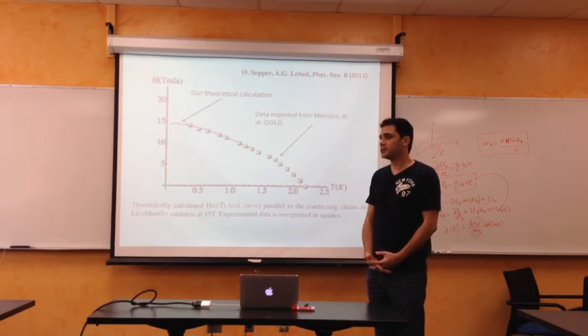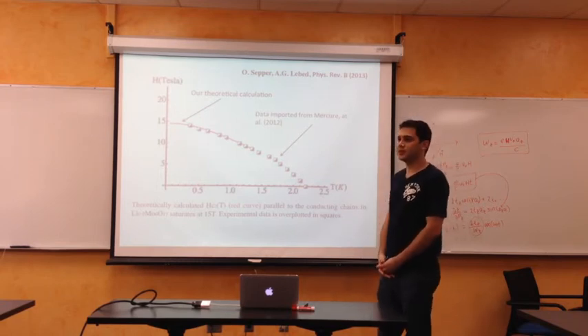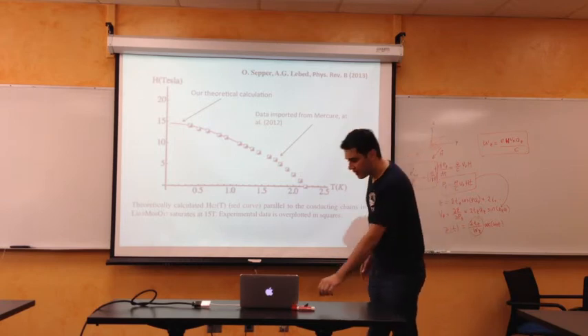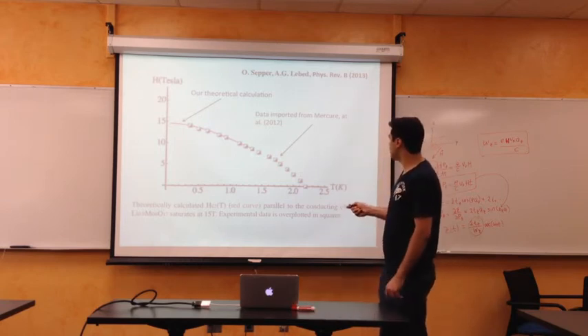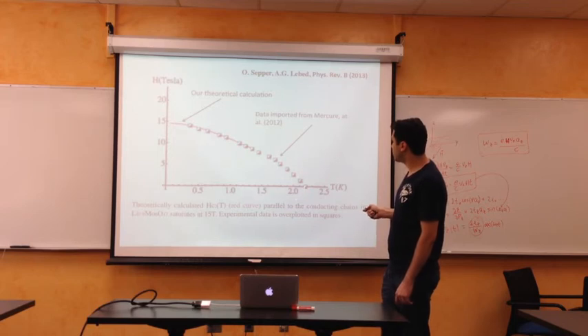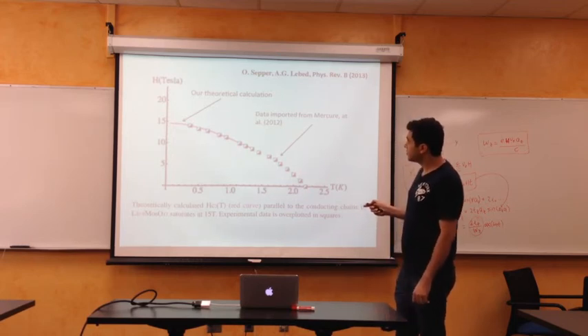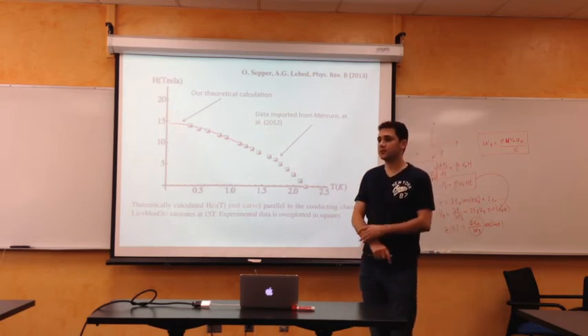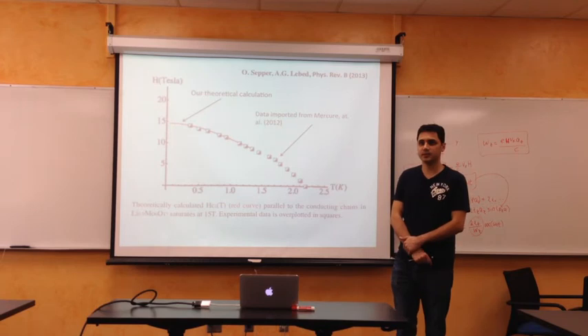It takes essentially a long time to solve it, yes, but the point is that we do expect deviation from this behavior at higher temperatures as we approach the Ginzburg-Landau limit near TC. But most importantly, at low temperatures, it shows the saturation which is important for the triplet case.